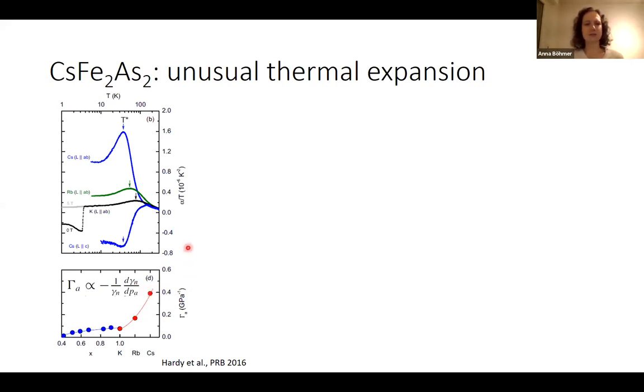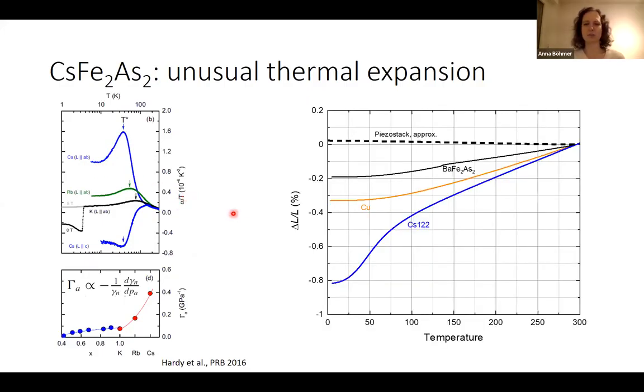We just talked about Grüneisen ratios, which is here the in-plane pressure derivative of the Sommerfeld coefficient. And as a consequence, or almost analogous to this, the thermal expansivity, the alpha coefficient here, is huge in the cesium compound. And I can plot not the alpha, the thermal expansion coefficient over temperature here, I can also plot simply the length change. What we see in the cesium-122, it shrinks a lot on cooling. It shrinks more than twice as much as copper metal, 4 times as much as barium-122, and very different from a piezo stack.